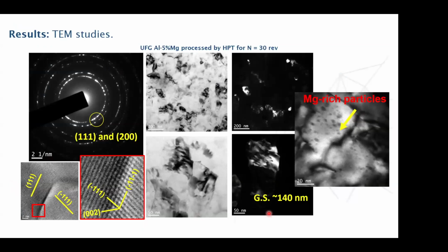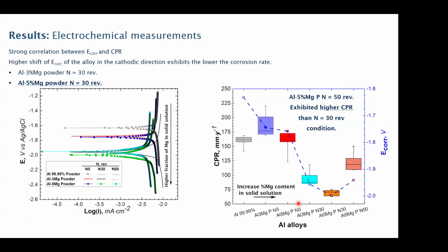So it's kind of a saturated magnesium aluminum microstructure, and it's probably driving some of the good behavior. It's ultra-fine grained, of course, and you can see here with the SAED pattern that the grains are very small with high angles of misorientation. And we can also see this kind of dispersion of the intermetallic particles, which is kind of the merit of the HPT process. The grain size is about 140 nanometers in aluminum. And we did see very good improvements.